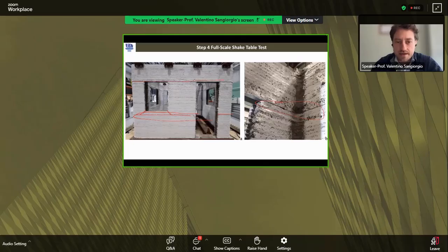Why is this interesting? Because the cracks occurred exactly in the position of the cold joint. So we can state that after this test, we demonstrated for the first time the importance of the cold joint compared with the opening.